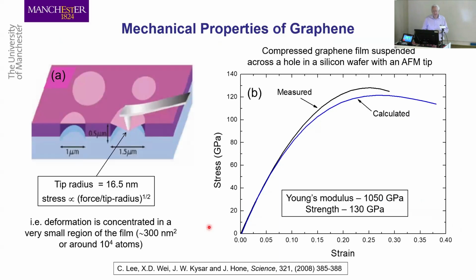So let's look at the first mechanical property measurement done. This was a paper in Science in 2008 by Jim Hone in the States. And they took a monolayer of graphene across a silicon wafer with holes in it. And they used a cantilever to indent the graphene, and they pushed it until it broke. And they measured the force and the displacement, and they generated a standard stress strain curve, stress against strain. And you can see here that they have a very high slope of the stress strain curve. This is the measured one.